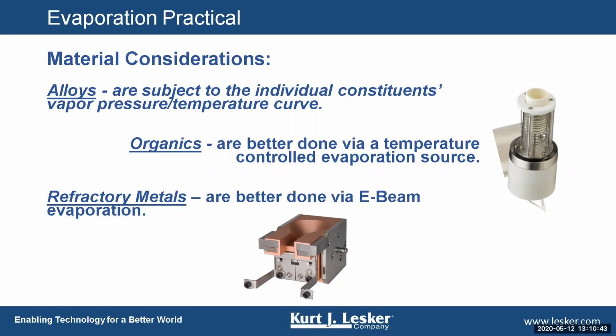Are there any materials you would run in an E-beam system without a crucible? Without a liner? It just depends. Absolutely. You can run material directly in the hearth pocket. Some materials are going to interact with copper, like aluminum and silicon. But I have run a lot of materials directly in the pocket, especially in production. When I worked in the production optics industry, most of our materials stayed set. In other words, we were always running, say, germanium out of pocket number 1 in an E-gun. So I didn't need a crucible liner. I just put germanium directly in the hearth pocket. The drawback is the possibility of cross-contamination if I decide to change the material in that pocket. I still might get a little germanium through that melt.